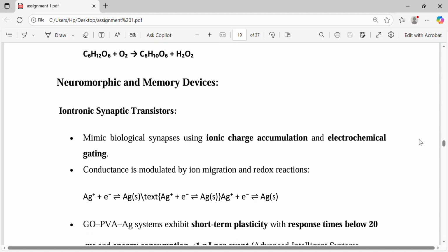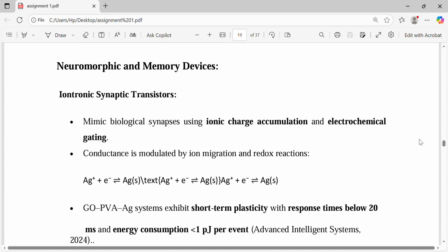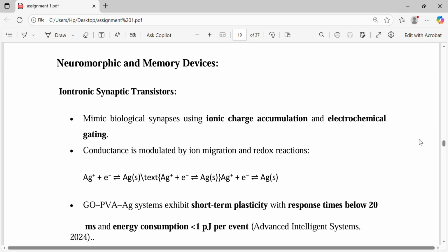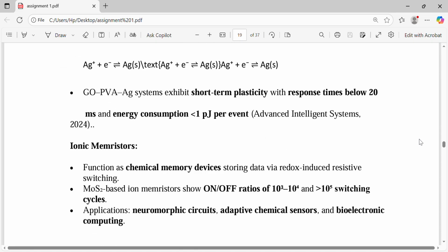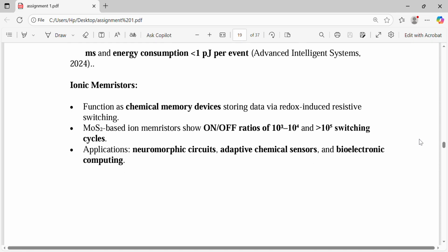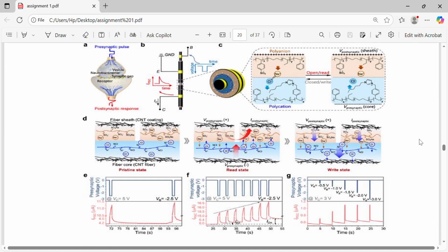Neuromorphic and memory devices. Iontronic synaptic transistors mimic biological synapses using ionic charge accumulation and electrochemical gating. Conductance is modulated by ion migration and redox reactions. Ionic memristors function as chemical memory devices, storing data via redox-induced resistive switching. MoS2-based devices show on-off ratios of 10^3 to 10^4 and 10^5 switching cycles. Applications: neuromorphic circuits, adaptive chemical sensors, and bioelectronic computing.